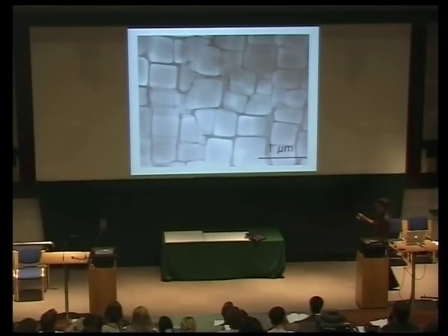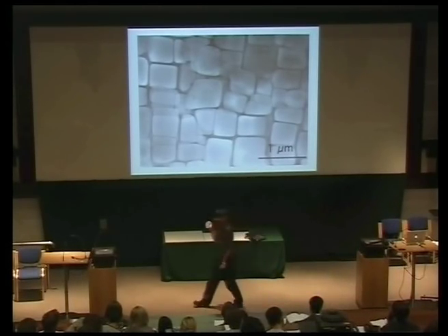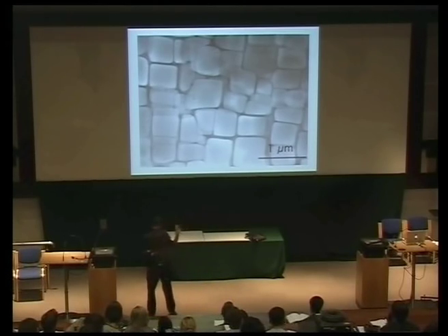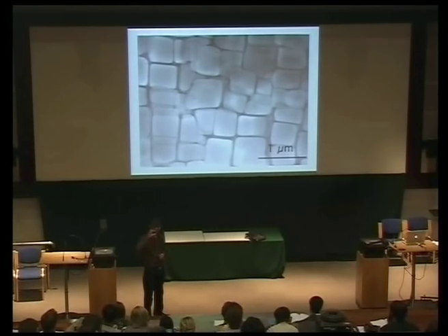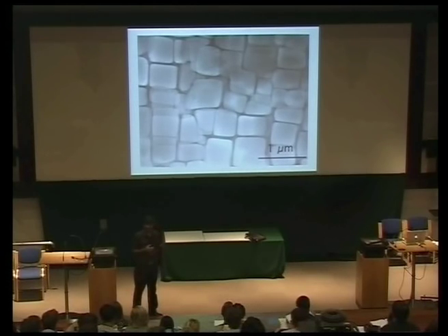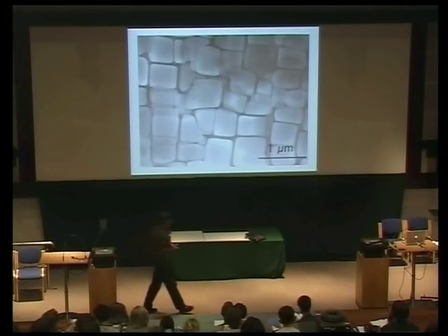So this is what the structure of one of those turbine blades in the hot end of the engine looks like. We have about 70% of gamma prime. This doesn't look like 70%. It looks a lot more than 70% because we are looking through a lump of material, so there's a lot of overlap of information. But you can measure this accurately using many methods, and it's about 70% gamma prime.